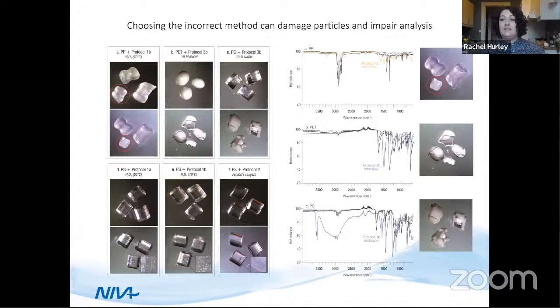So we've tested some of the different approaches here at NIVA. We observed that some of the digestion protocols that are used in other examples to remove organic material, not necessarily in microplastic analysis, when these are used at high concentrations or high temperature, it is possible that it can damage plastic particles. And we can see some examples here where the surface of the particle is damaged after exposure to the different reagents, or the size of the particles is significantly reduced.